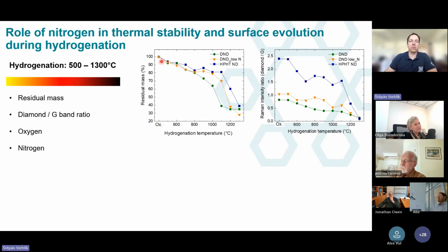So this is the residual mass. You can see here that initially we see a decay of the residual mass, which is associated with the hydrogenation. It's a replacement of the original heavier oxygen on the surface by lighter hydrogen and formation of the CH bonds. But when we go higher with the temperature, we exceed some stability limit, and we see the graphitization, which is connected with the mass loss, because the hydrogen is still a bit of a reactive atmosphere, so the particles are actually gasified. And this correlates with the Raman intensity diamond to G-band ratio.